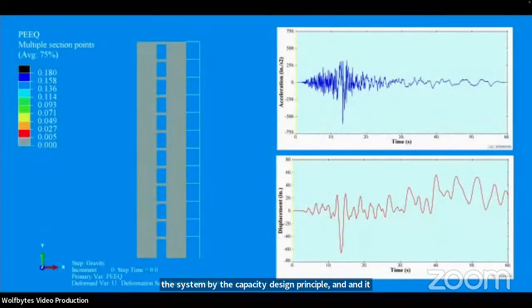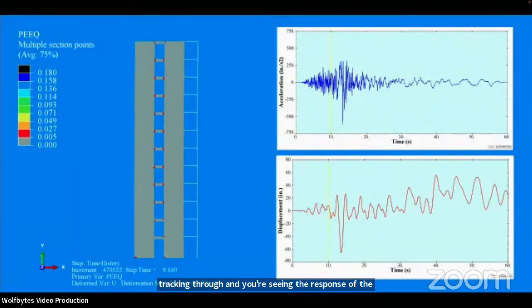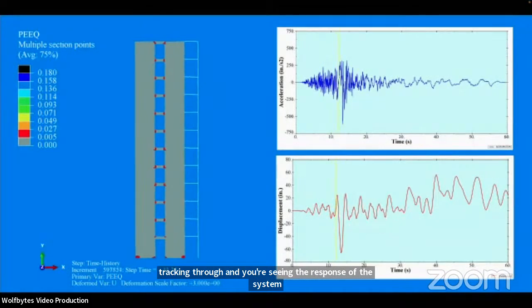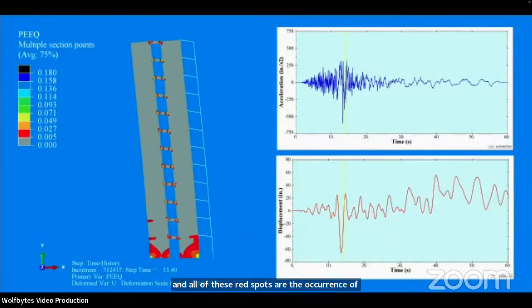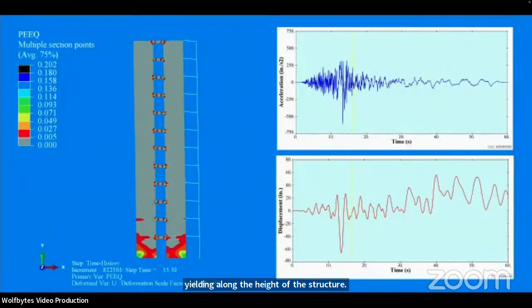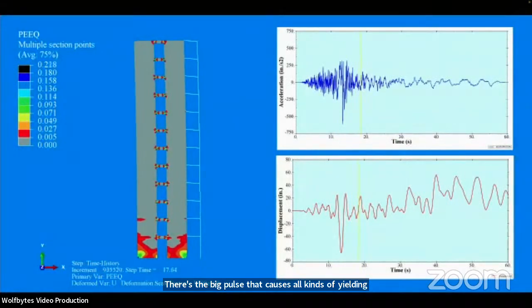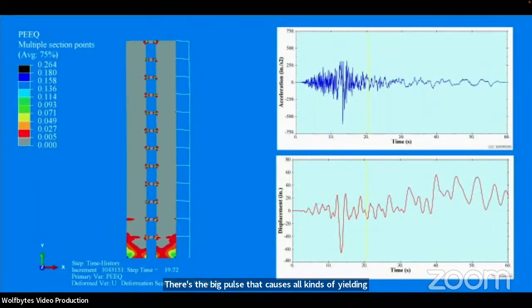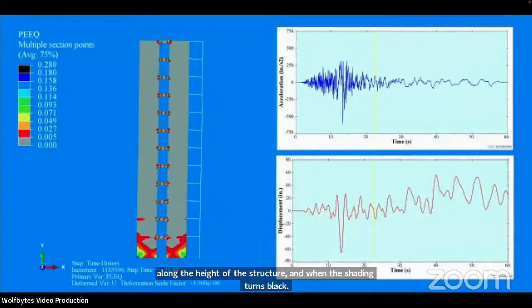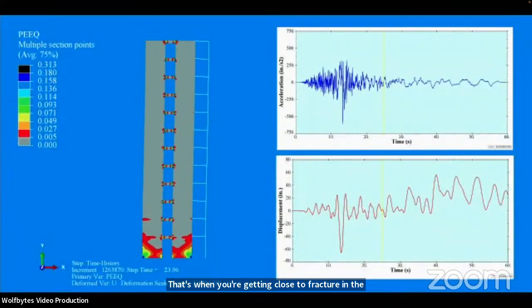This is a video that actually shows the seismic response of a 12-story structure where you can see the ground motion as it's tracking through, and you're seeing the response of the system. And all of these red spots are the occurrence of yielding along the height of the structure. There's the big pulse that causes all kinds of yielding along the height of the structure. And when the shading turns black, that's when you're getting close to fracture in the coupling beams, which has occurred for some of these coupling beams along the height.